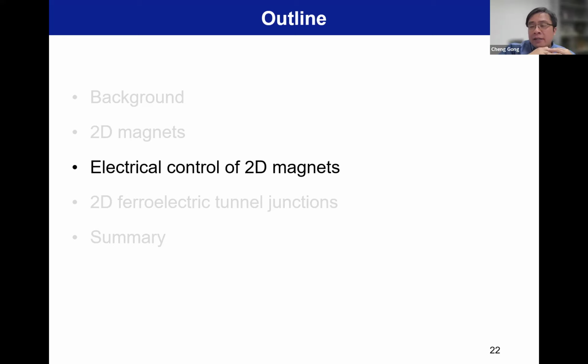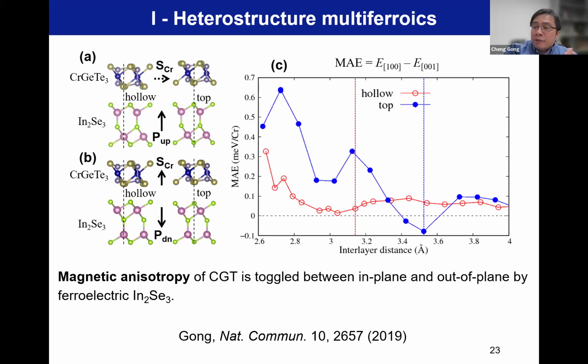We did not talk about ionic control here. It's a little bit complicated, and there is still a lot of debate, because the ions can easily intercalate in the material and even strongly bond and cause structure distortion or new chemical substances. So we just talk about these two. As you can see, electric field control or electrostatic doping control sounds not that energy efficient from the back of envelope calculation. So here, I will first show three parts of theoretical work and then move on to our experimental work.